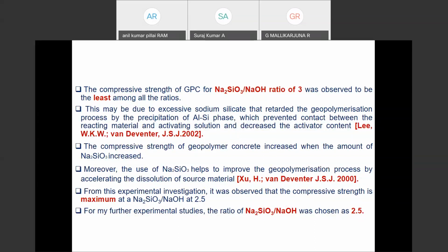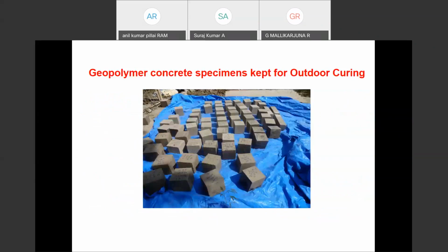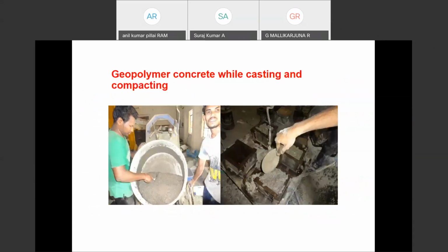And the experimental investigation shows that the maximum strength is at a sodium silicate to sodium hydroxide ratio of 2.5. And after that, we had the limitation that we removed the specimens. We did not go for oven curing. Why? Because we have to produce the concrete in in situ condition. For that, we prepared the specimens and left them out for outdoor curing. The casting was the same as how we prepare ordinary conventional concrete. Same pattern we followed